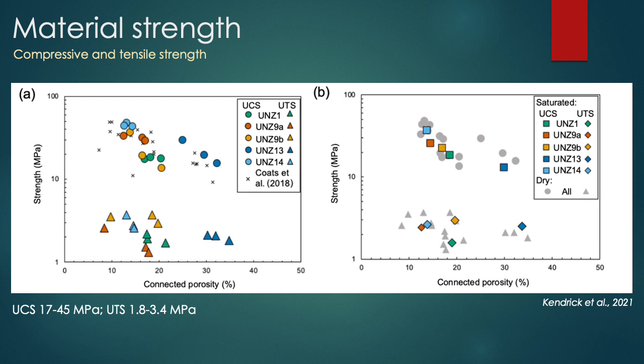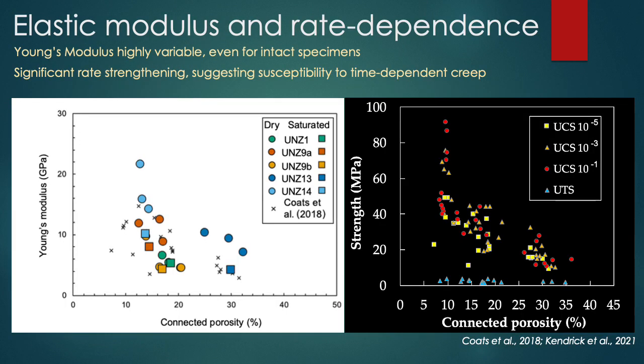We also performed the same tests on saturated samples to see whether saturation itself, caused by rain at the volcano, could weaken the materials, but we found that the results were largely indistinguishable from the dry tests as shown by the plot on the right. We did, however, find that Young's modulus was slightly reduced by sample saturation, although this did not particularly extend the span of values, which was already from 4 to 22 gigapascals.